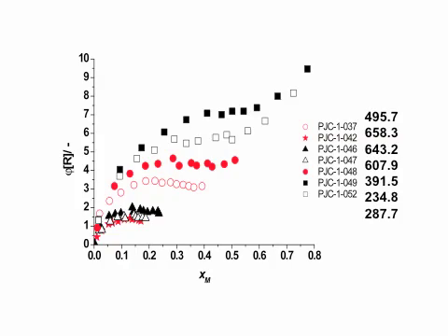And then for the smaller particles, you see that there's a massive increase in rate of reaction. Now there's a few distinct regions. So you see these plateau numbers here, these leveling out bits here. And that's an indication of where you want to be. So you know, the smallest particle polymerizes 7 times as fast as you would expect based on bulk kinetics.